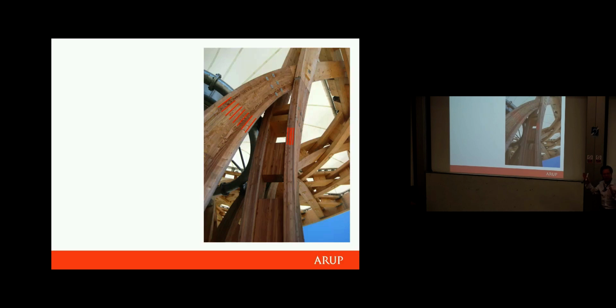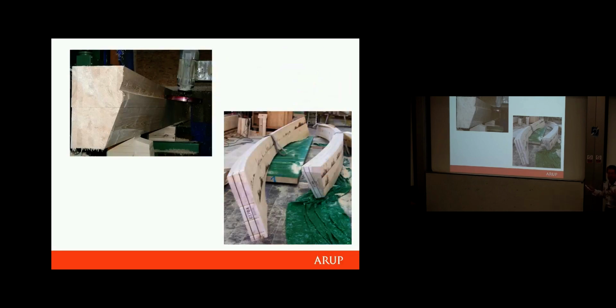What's interesting is that the winning fabricator realised that rather than making doubly curved twisted members everywhere, which was going to be really expensive, a lot of them they could simply machine out of straight glulam. A straight glulam, like on the left, you can buy really cheaply, about £400 a cubic metre. In fact, the price has effectively fallen by 30% in the last 15 years. So really, really cheap. We've got a big oversupply in Europe. And there you can see the CNC machine starting to machine that glulam down into these tiny little members. Obviously there's a huge amount of machining time and a huge amount of wastage, but it's still cheaper than making a doubly curved twisted glulam member.